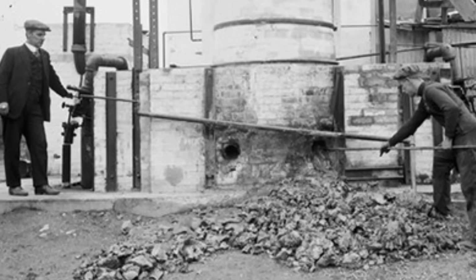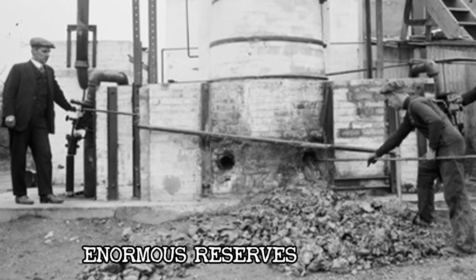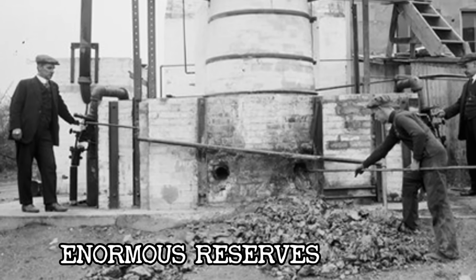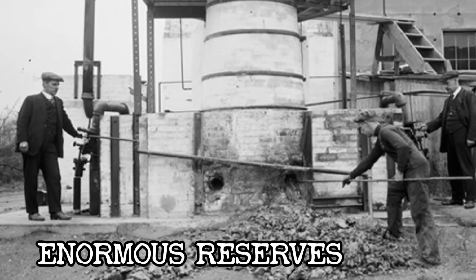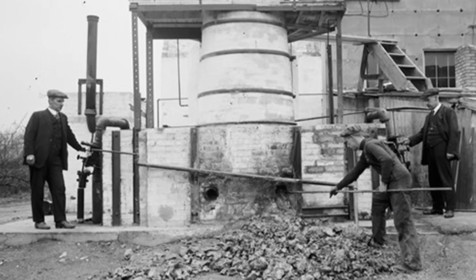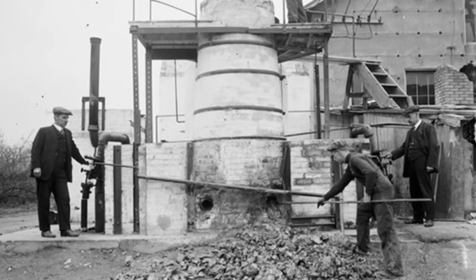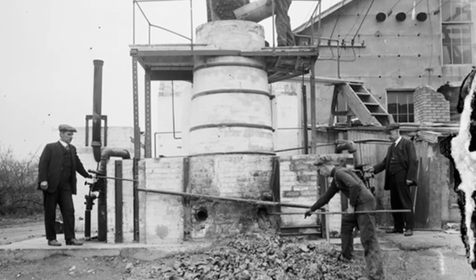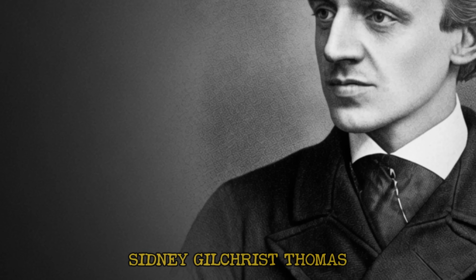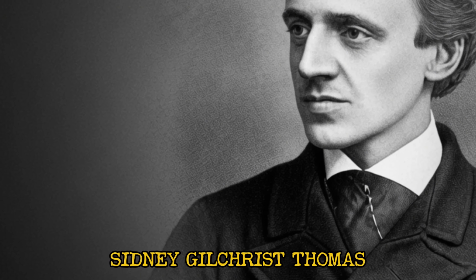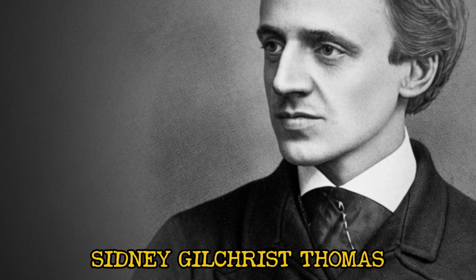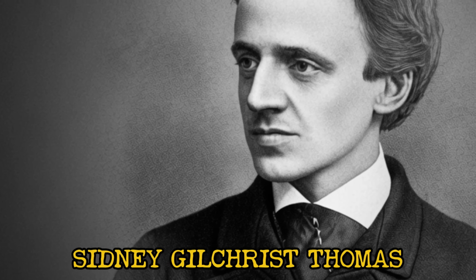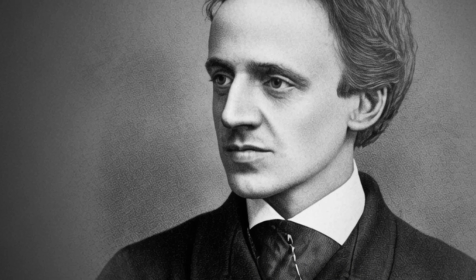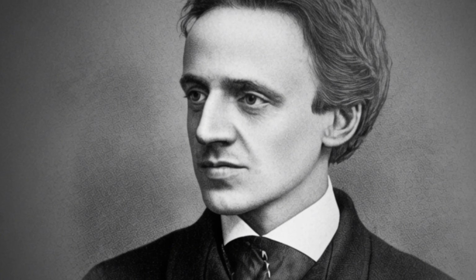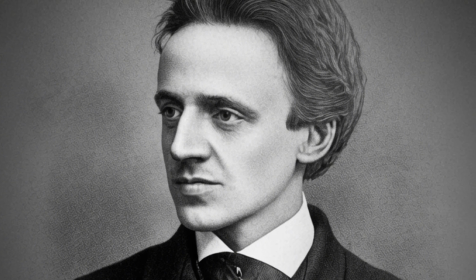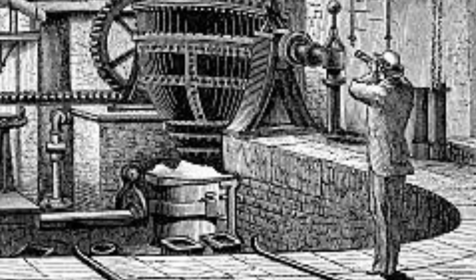Continental Europe, sitting on enormous reserves of high phosphorus ore, watched the Bessemer revolution from the sidelines, unable to use the very process that was making American and British steel barons rich. The fix came from an unlikely source, a young chemist named Sidney Gilchrist Thomas, working largely alone and outside the major steel companies. He identified that swapping the converter's interior lining from acidic clay to a basic material like burned limestone or dolomite allowed phosphorus to be drawn into the slag instead of ruining the steel.